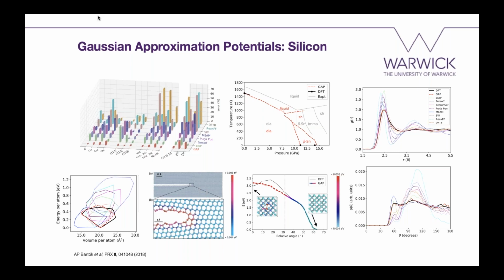So this is a comparison between a number of interatomic potentials for silicon, all benchmarked against density functional theory. Red is our model, GAP, and then all the others are shown in different colors. This figure is split into two parts. On the left, there are tests which we expect to get right from the training data we used for fitting the potential. And on the right, we are trying to explore how transferable it is and how well it can extrapolate into unknown configurations.